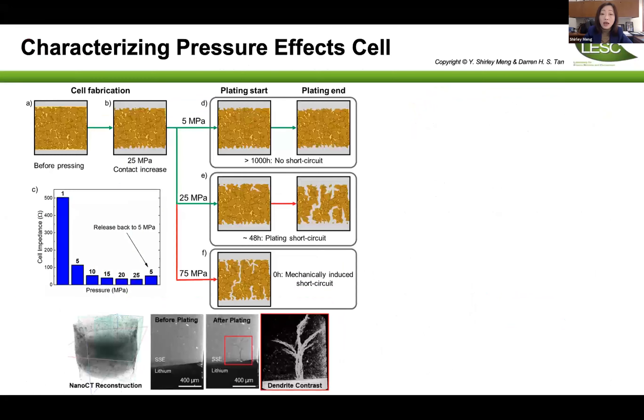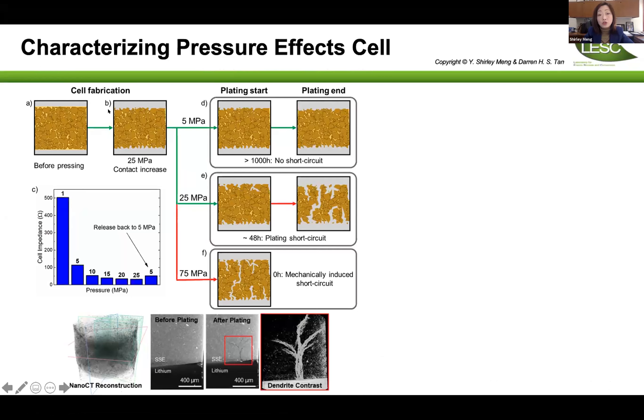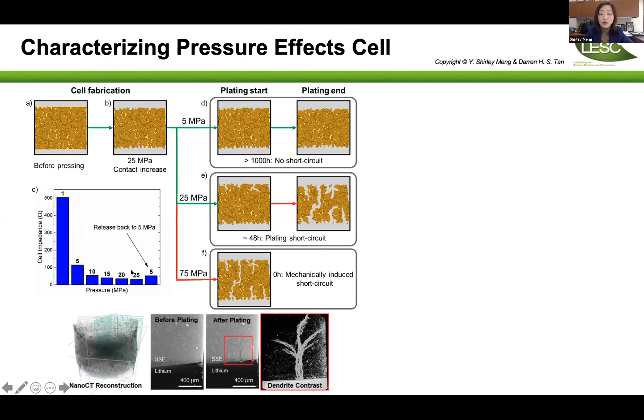Another very important parameter — and potential showstopper for solid-state battery commercialization — is pressure. In solid-state battery synthesis, you have to apply very large pressure: 25 MPa is what we do in the lab, and I've seen industry numbers like 75 MPa. In the early days, high pressure was emphasized to establish good solid-solid contact and reduce cell impedance. But because of this, many researchers found that lithium metal dendrites propagate through the solid-state electrolyte when cycling around 25–75 MPa.